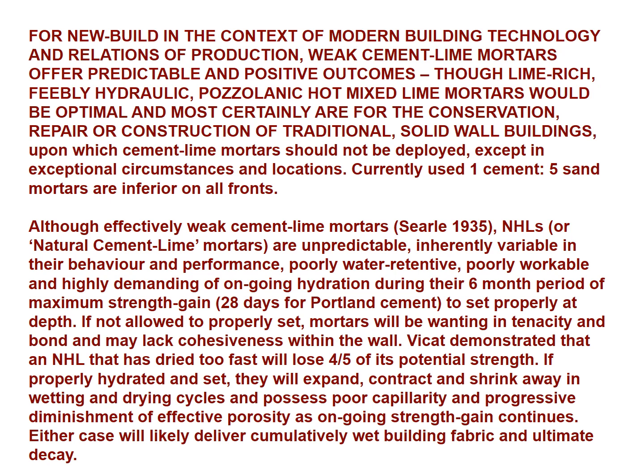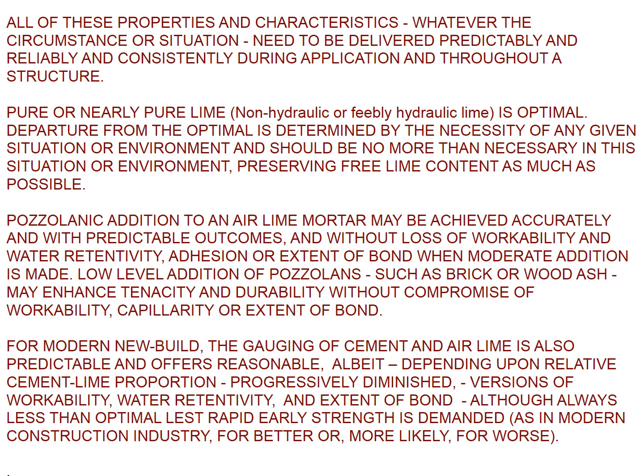If not allowed to properly set, mortars will be wanting in tenacity and bond and may lack cohesiveness within the wall. If properly hydrated and set, they will expand, contract, and shrink away in wetting and drying cycles, depending upon their extent of hydraulicity, and possess poor capillarity and progressive diminishment of effective porosity as ongoing strength gain continues. Either case will likely deliver cumulatively wet building fabric and ultimate decay. All of these properties and characteristics, whatever the circumstance or situation, need to be delivered predictably and reliably and consistently during application and throughout a structure.